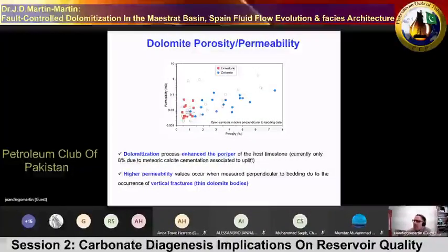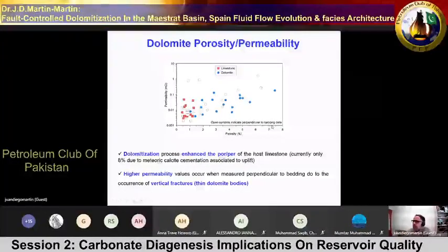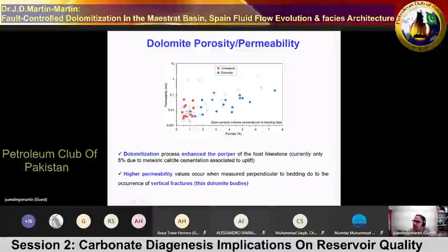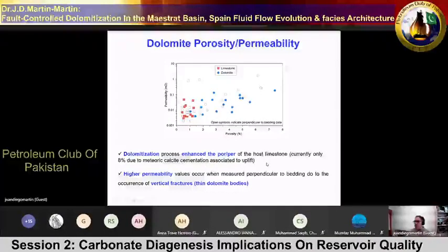This is a dolomite porosity-permeability plot, also showing the limestone. The limestones are square symbols. The dolomites are round. Open symbols indicate perpendicular to bedding data, and as you may see, this is the data we were showing before: limestones with very low porosity and permeability, and we see an increase in the dolomite porosity and permeability with respect to limestone. So dolomitization enhanced porosity and permeability of the host rock.